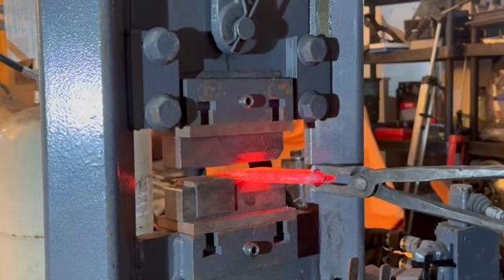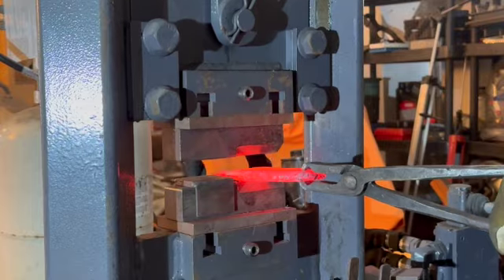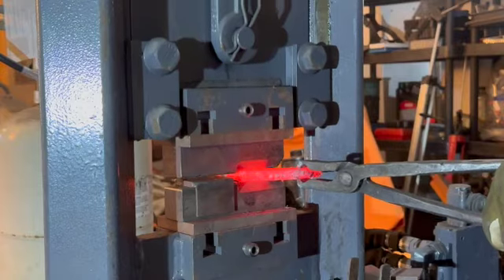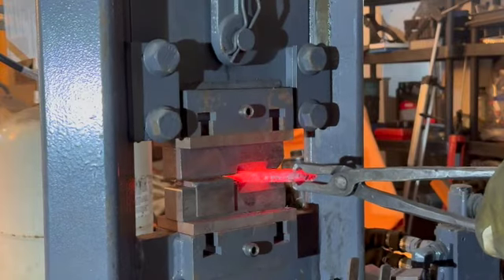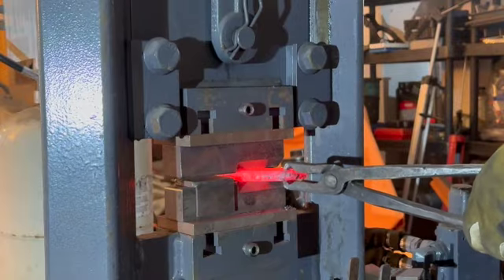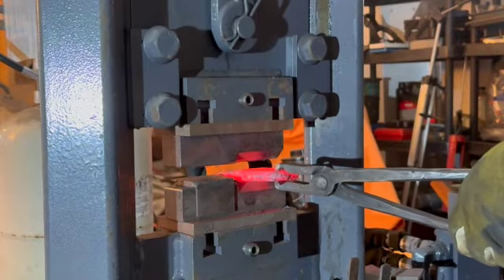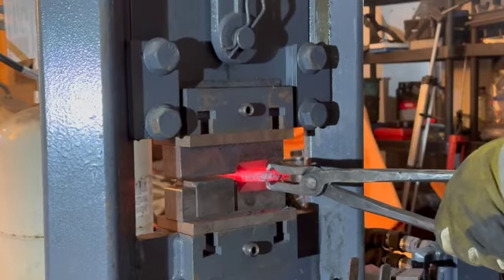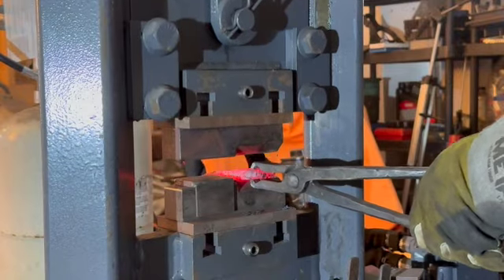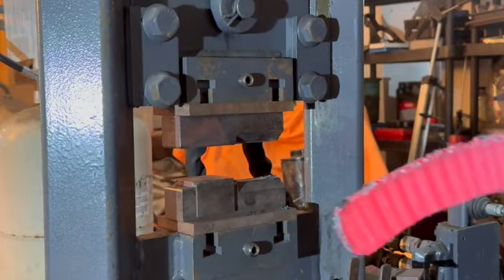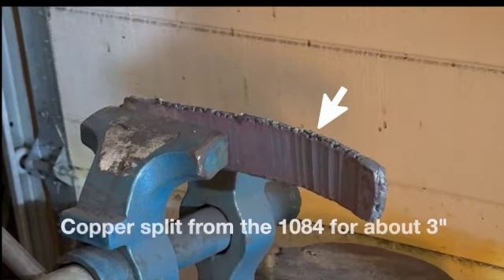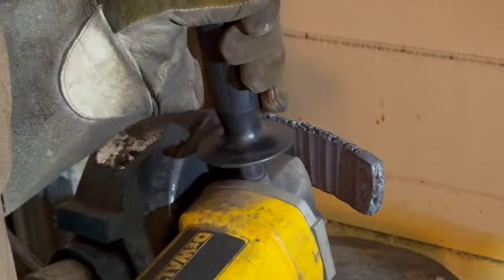Now I ran into a problem here. I was hoping to make enough steel for 2 knives. I ended up only getting 1 out of it because, as you can see, the steel is curving due to the press. I should have been more careful, and I wasn't. What happened when I tried to straighten it out was half of the billet delaminated along the copper. So we end up with another hunk of steel for the scrap pile. So much for 2 knives out of this billet.